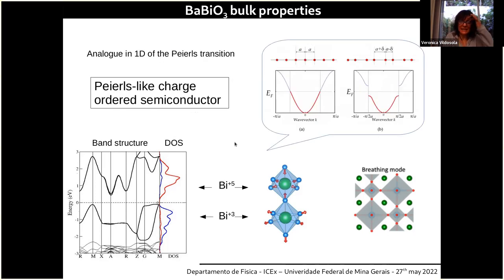Great. This material, barium bismuthate, is called a Peierls-like ordered semiconductor, in analogy to the Peierls transition. And I can describe the Peierls transition very simply. If you have a one-dimensional chain of atoms with a unit cell with lattice parameter a, and each atom has only one electron, and you perform a tight-binding model with one band, you end up with the band half filled, and you have a metallic situation. But if for a given reason you have some dimerization, for instance, that forces the system to double the cell, and you have two ions per cell,